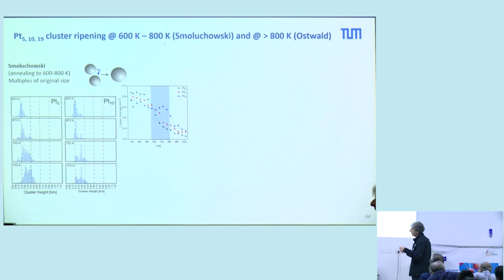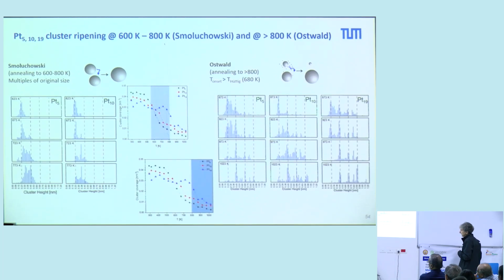This is also shown by the height distribution of the clusters. As a function of temperature, you see a broadening of the peak. That means you have the initial state, which are encapsulated platinum 5, platinum 10, and if you go to higher temperature, you have double the size. That means you produce larger clusters. You have this Smoluchowski ripening. And then if you go in further, you see that the coverage remains, but you have a very broad cluster distribution or size distribution.